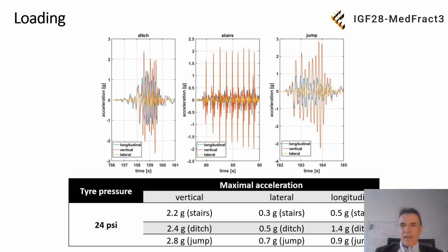Based on this measured data, after some processing such as filtering, it has been possible to define the dynamic factors in these key operational states: the ditch, stairs, and jump. Down in this table, these results are documented as a dynamic coefficient in the vertical, lateral, and longitudinal direction. For these 3 operational states, all the measurement was made at 24 psi tire pressure, which is recommended by the producer.